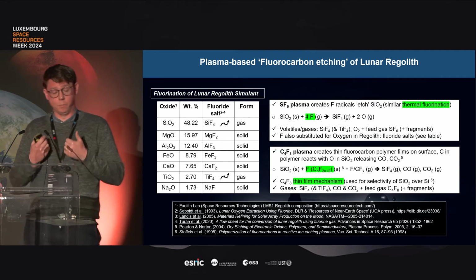So in terms of the SF6 plasma that we've shown, we expect that the mechanism is quite similar to a thermal fluorination, and indeed with the heated plate we may have some of that going on, in that the atomic fluorine is interacting with the oxides to abstract the oxygen.